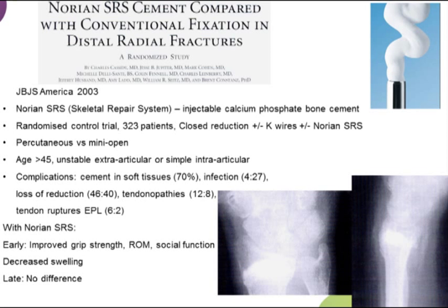So just back to mention some of the cement. Those were the block forms, and this is a cement form. Cements are dissolved forms of calcium phosphate. As you probably know, with a cement, a precipitation reaction occurs in vivo when you implant it, the calcium phosphate crystals grow, and the cement hardens. The benefit is that you can custom fill bone defects or bone voids, and therefore get better conformity through that bone void. However, the major disadvantage is the risk of extrusion of cement from the site that you're implanting it at.